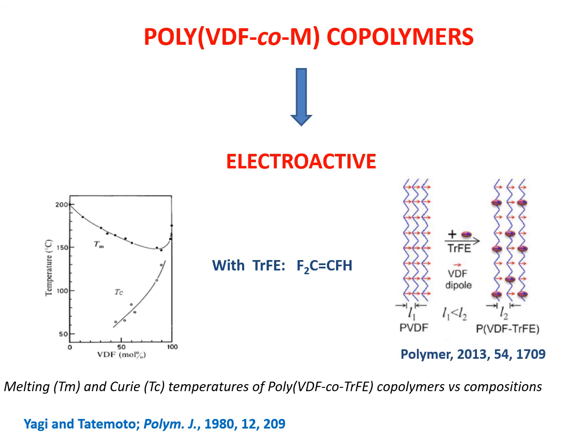Indeed, the system relies on the different interlamellar layers, in which the bulky trifluoroethylene is going to force some free distance of VDF, showing that L2 here is higher than L1, in which the crystallization can occur and favor the beta phase.